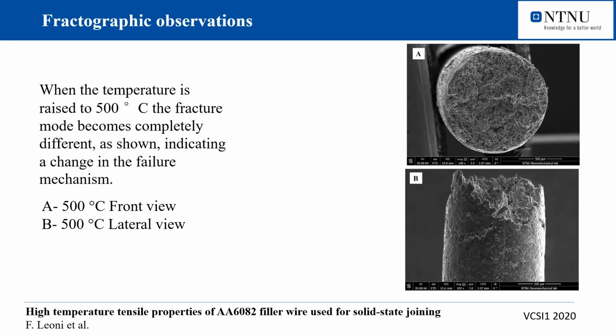But when the temperature is raised to 500 degrees Celsius, the fracture mode becomes completely different, as shown here in the figure. This indicates a change in the failure mechanism. At this temperature, necking is no longer noticeable. Figure B shows a lateral view of the same fracture surface. It appears rough, probably because intergranular slip and grain boundary sliding become predominant at high temperatures, which, in turn, promote separation between grain boundaries when the material is subjected to tensile stress. This type of failure, being associated with negligible necking and intergranular slip, is typical of creep rupture.